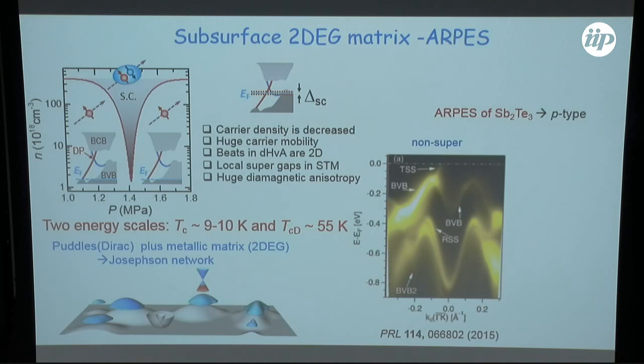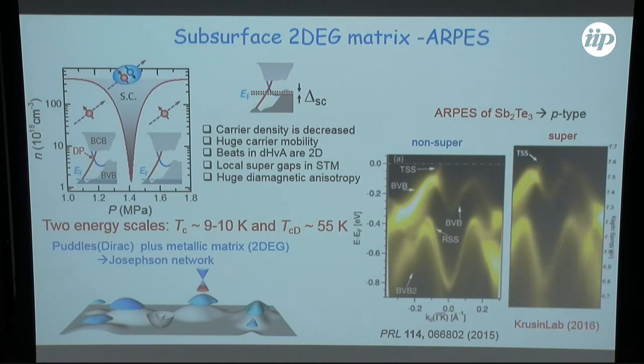This is actually published data by another group. Remember, this is a standard ARPES, and since these systems are p-type, you can only see the states up to the Fermi level, right? So you see this. This is part of this surface state here, which continues over there, and this was published data on this material. This is our superconducting sample, and it looks the same. But the question now was, okay, so what about all the stuff that is subsurface? Whether that can give us some sort of a clue as to topological or proximal superconductivity, if you will, in this surface system.